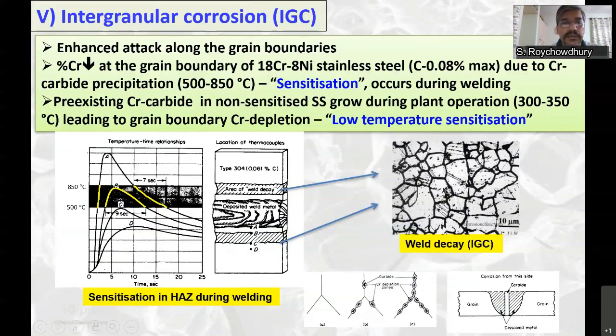During welding, as shown here, this is the weld deposit. This region away from the weld is exposed to this temperature range of 500 to 850. And not only that, the residence time, which is given by this temperature variation here, the residence time within this temperature range of 500 to 850 is much longer for this region from B to C. This curve corresponds to point B, and this is the curve for point C. So all this region between B and C, the residence time is much more.